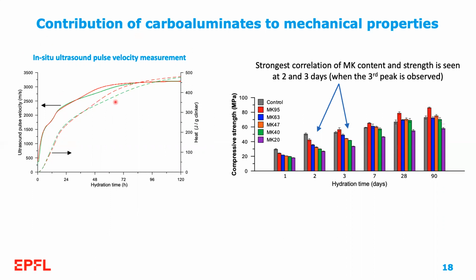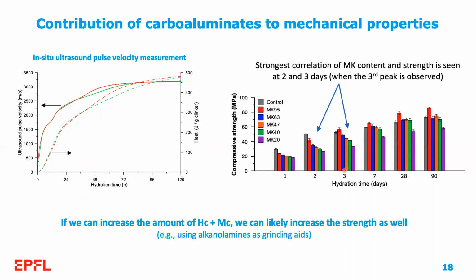So this tells us that the formation of these carboaluminates is leading to a quantifiable and measurable reduction in porosity and increase in mechanical properties. And this is very interesting because it's really where this separation occurs, between 2 and 3 days of hydration, that we see the highest correlation between metakaolin content and compressive strength of our LC3. Then we can also conclude that if we can increase the amount of hemi and monocarboaluminates, we can likely increase the strength properties of our LC3 as well.